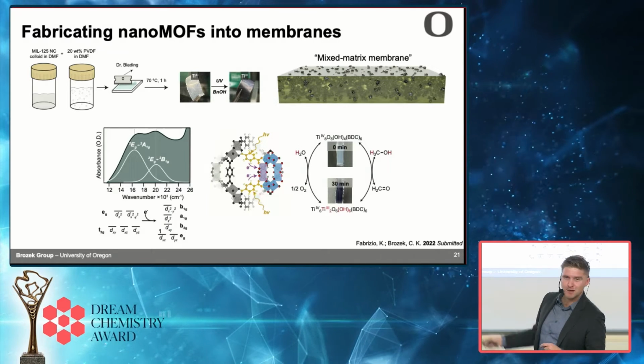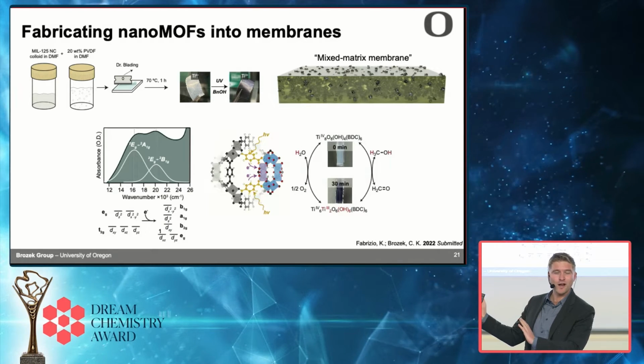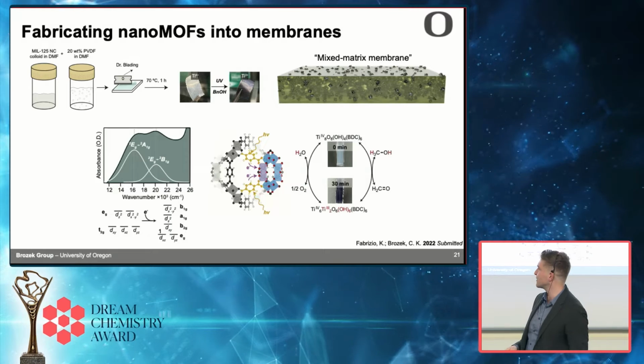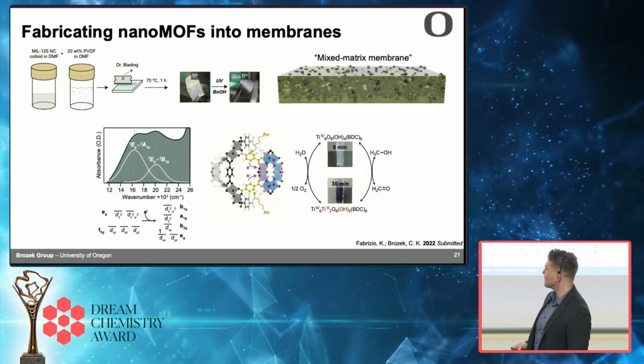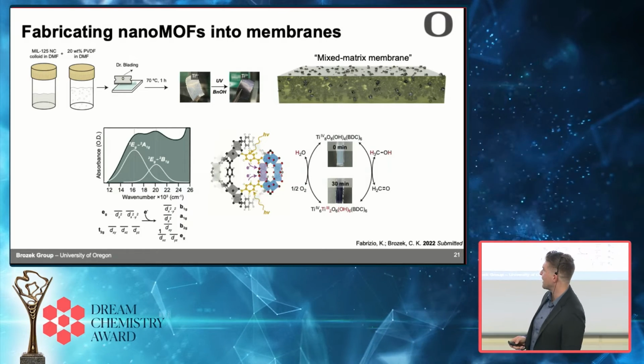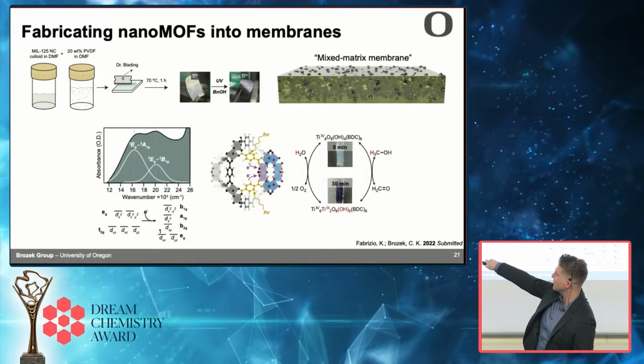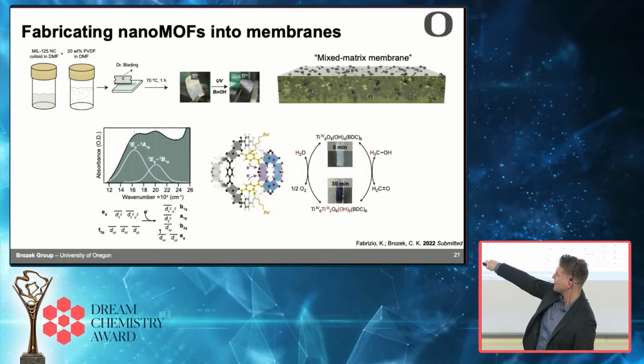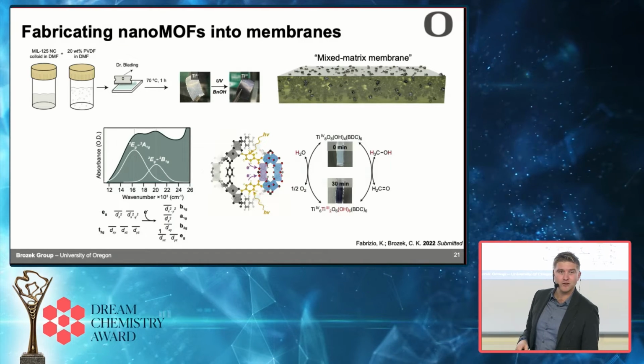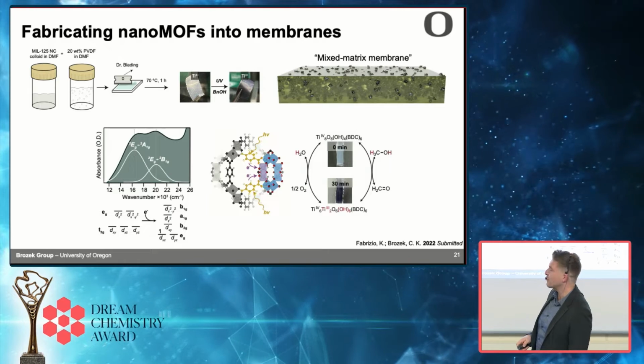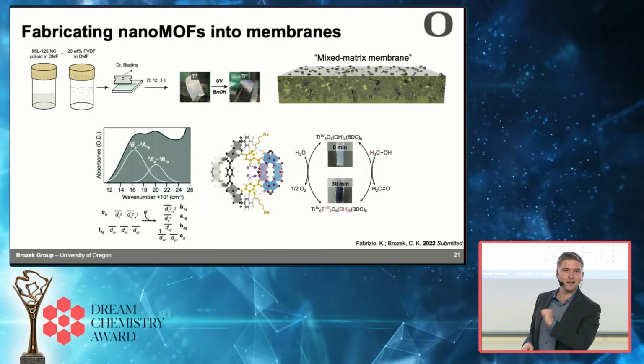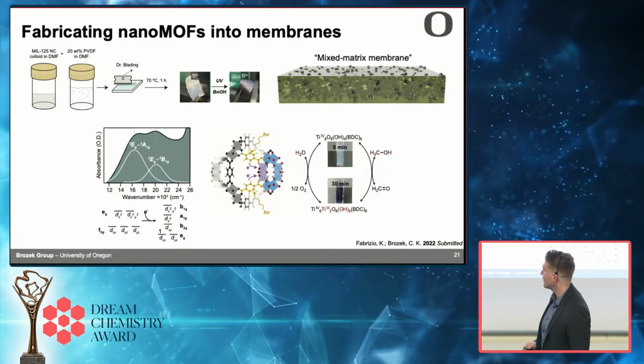Titanium 3+, subject to Jahn-Teller distortion. We can quantify all of it. We can quantify that Jahn-Teller splitting. And the other thing that we know is that this definitively proves this mechanism, that light comes in, you excite an electron from the linker to the metal, and you trap the electron on the titanium by quenching that hole on the linker with an alcohol.